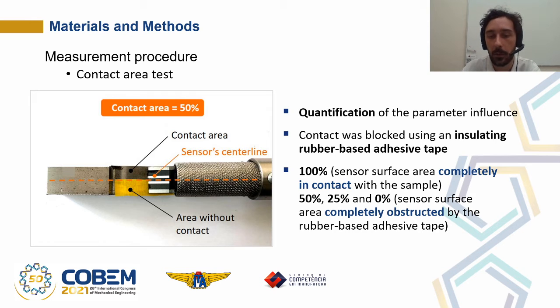tests, the contact area was varied as a function of the percentage of the sensor surface area in contact with the sample. These tests were divided into 100%, where the sensor surface area is completely in contact with the sample, 50%, 25%, and 0%, where the sensor surface area is completely obstructed by the rubber-based adhesive tape.